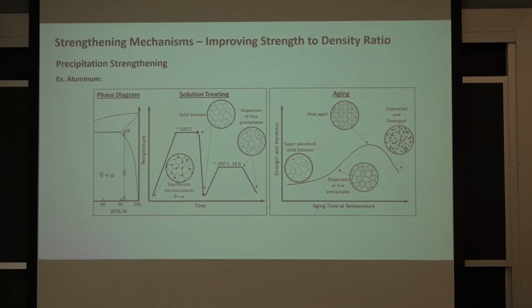There becomes a time where the strength peaks. You get a fine distribution of many, many fine little coherent precipitates, and the strength of the material peaks. Hopefully when you buy your 6061 from, I don't know, McMaster Carr or down the street, wherever the mill is, the material is going to stay there during its whole life. And you can rely on that material to have that strength when it's reached its peak strength.